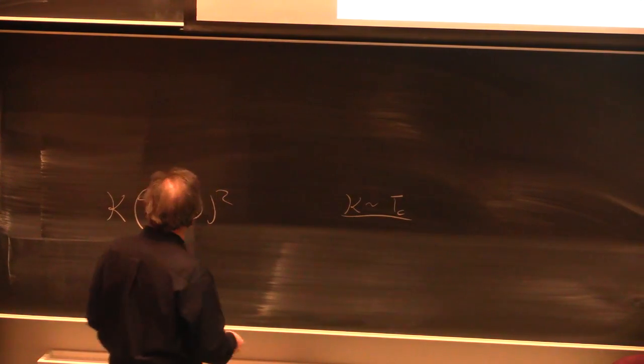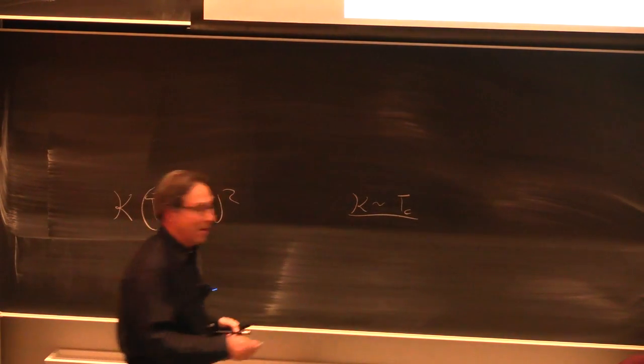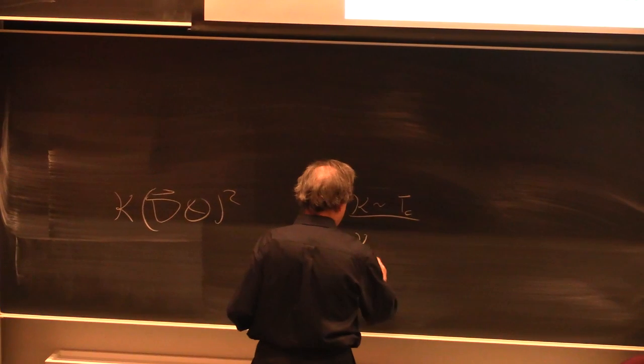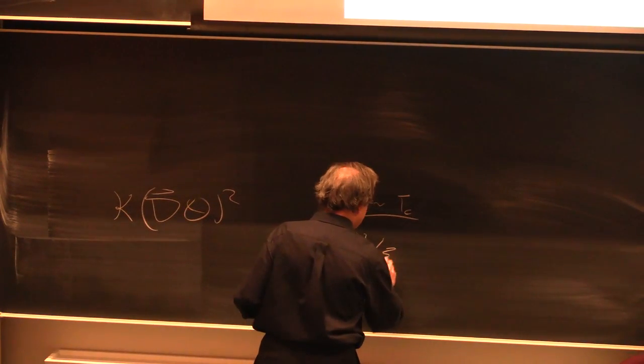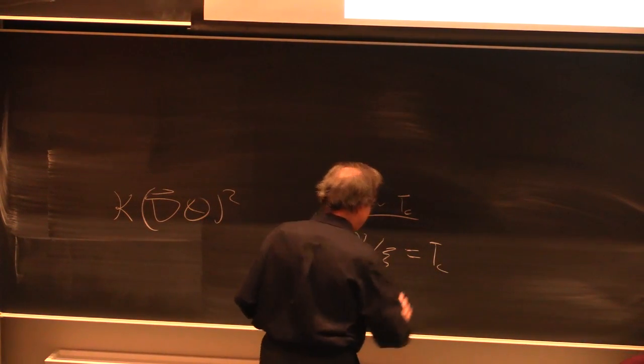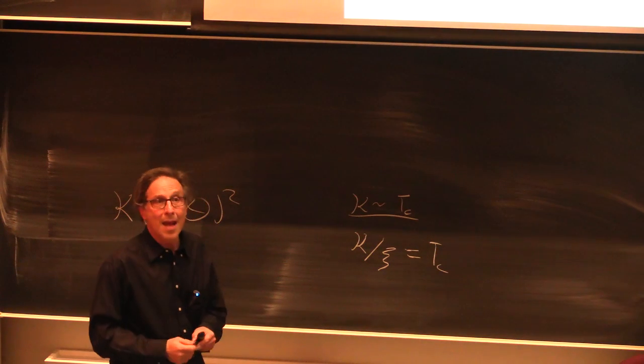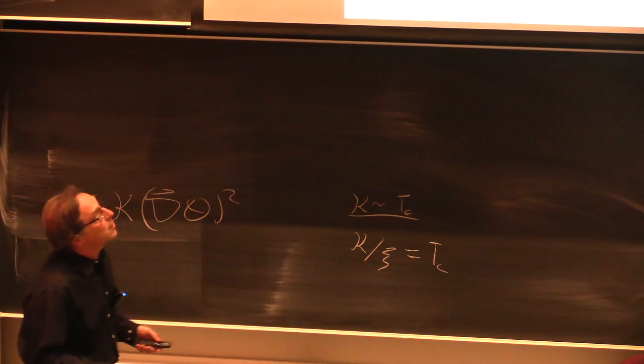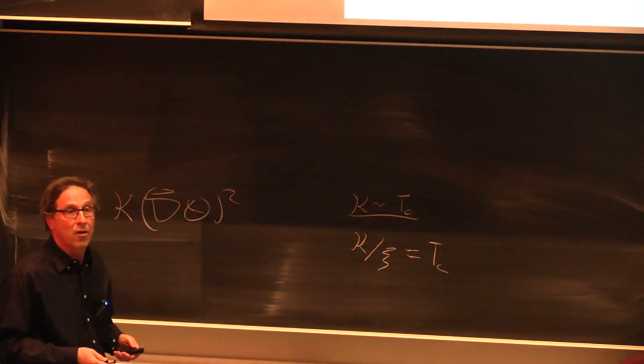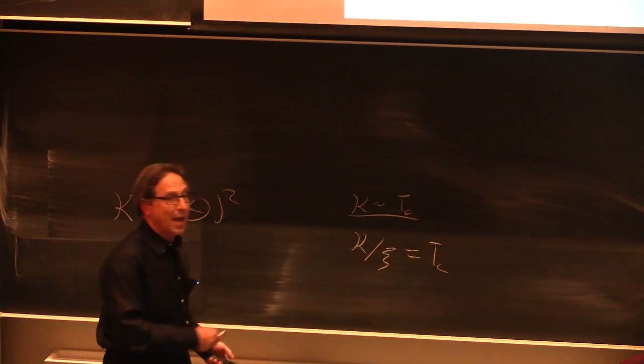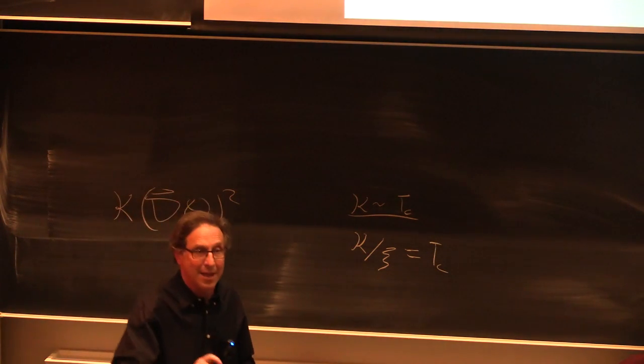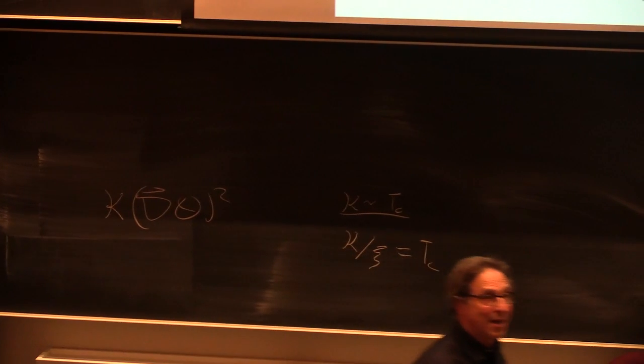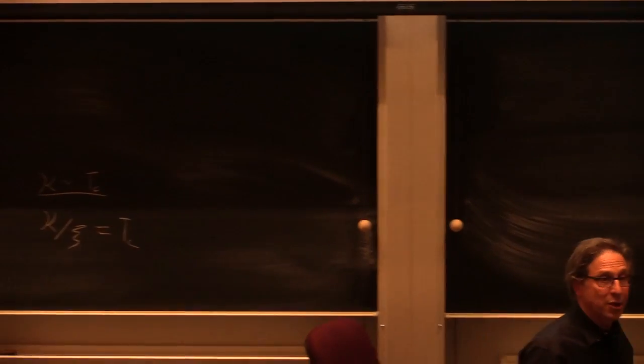In 3 dimensions, we need a length scale here. It's kappa over some length scale that's equal to Tc. So in the cuprates, fortunately, since they're layered materials, this length scale is just the spacing between planes, and everything's easy. If you're looking at a more three-dimensional material, probably that should be taken to be the zero temperature coherence length.